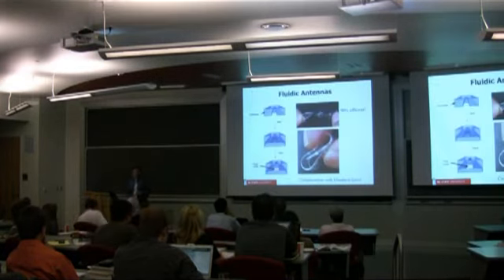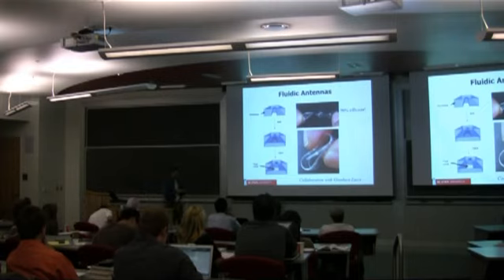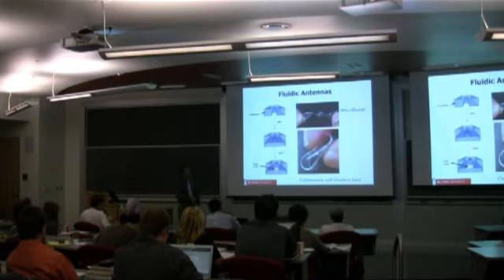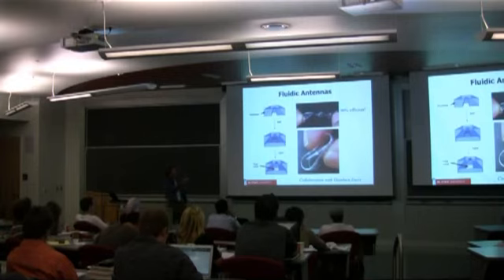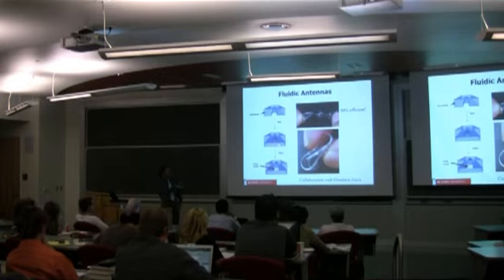Okay. So a much easier way to shape this metal is using what's called microfluidics. These are basically just very small tubes. And we can do this very easily using a material that's sort of like bathroom caulk. It's called PDMS, but it's not all that important. We basically mold the material. So this is a squishy material, which we seal to another flat piece of the same material. And then we inject the metal. We literally do it by hand. You can use a syringe. It's extremely simple. And we formed a dipole antenna.